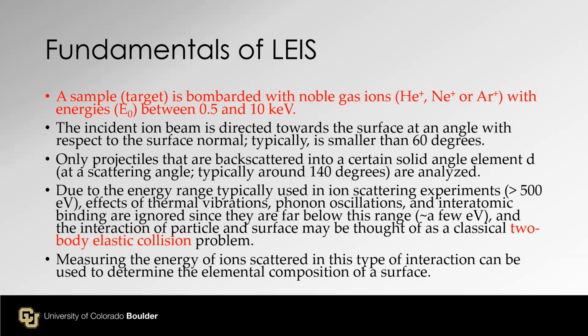Our QTAC incident beam is normal to the surface, at 0 degrees. Only projectiles that are backscattered into a certain solid angle are analyzed, about 140 degrees from the incident, so about 40 degrees from the surface normal.